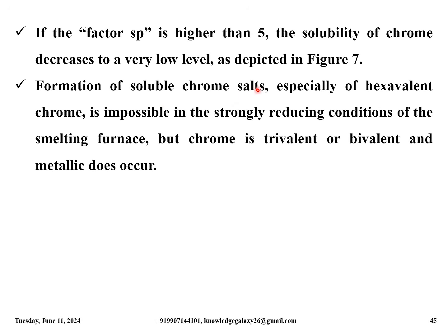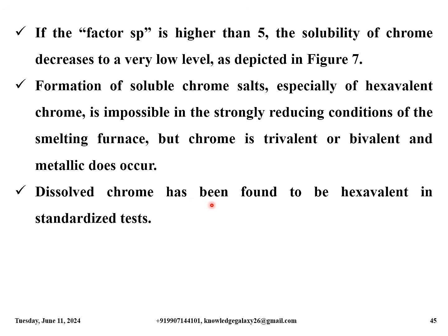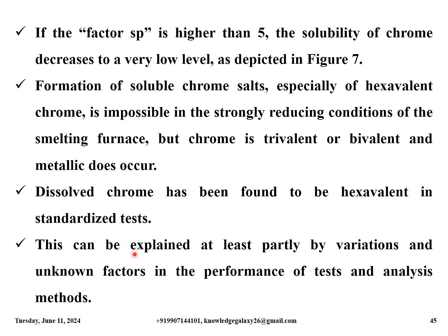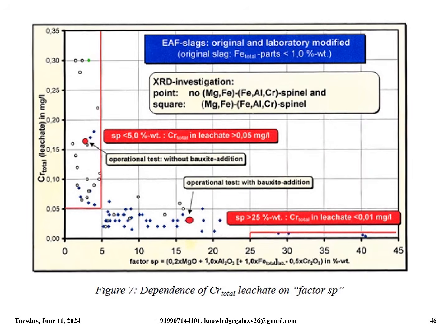Formation of soluble chrome salts, especially of hexavalent chrome, is impossible in the strongly reducing conditions of the smelting furnace, but chrome in trivalent or bivalent and metallic form does occur. Dissolved chrome has been found to be hexavalent in standardized tests. This can be explained at least partly by variations and unknown factors in the performance of tests and analysis methods. So this is figure 7, which depicts the dependency of chromium total leachate on factor Sp.